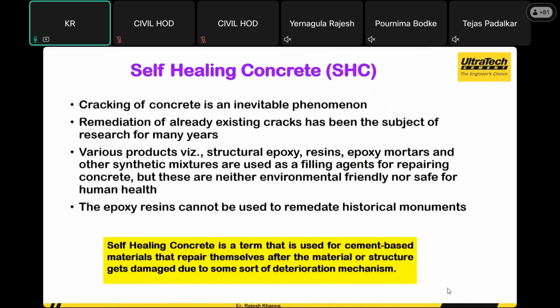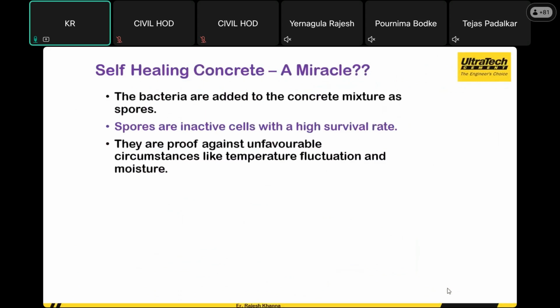When we are talking about concrete in a big way, we also see that concrete has a natural tendency to crack. Cracking of concrete is an inevitable phenomenon. We cannot even stop it. We have to control concrete from cracking by having certain remedies and systems in place. But now we have a concrete called self-healing concrete, where concrete can heal on its own. This is a cement-based material that repairs itself after the material or structure gets damaged due to some deterioration mechanism. It means not all structural cracks may be addressed, but any micro cracking or macro cracking can be healed on its own, because it is just like bacteria added into the concrete during the time of batching.